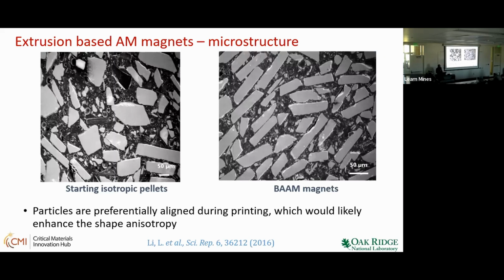One thing with this extrusion process is that we looked at the microstructure of the magnet. That's the key when you come down to the micron size, so the microstructure is very important. If you look at the SEM where the particles are in a polymer matrix, you see random orientation. But during extrusion, even without applying a magnetic field, you see some alignment, so you see some improvement in properties.